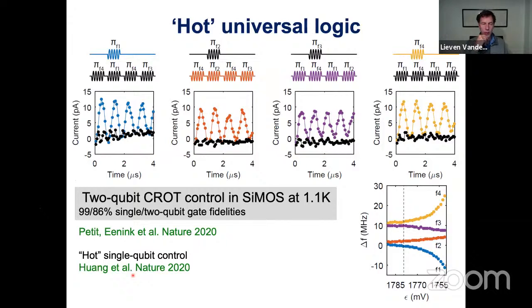We've learned along the way also about how the higher temperature impacts phase coherence and relaxation. For energy relaxation to the ground state, there is a very clear and expected dependence that has to do with an increased phonon occupation by raising the temperature. And then for the dephasing, the main mechanism that looks temperature dependent is charge noise, but other mechanisms appear to be temperature independent even. So we'll see where this trade-off is gonna bring us in terms of the operating temperature. But there is, I think, an opportunity to really make this work all together.